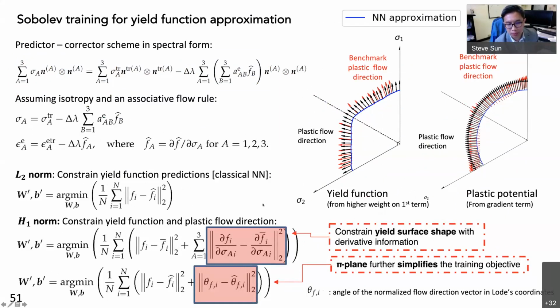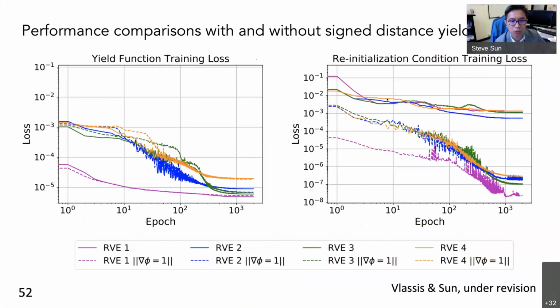We can also use the plastic strain increment to introduce a non-associative flow rule, as this example shows. We don't necessarily need to change a plastic potential. We can, but we can also compare the rotations between the stress gradient and the plastic flow direction to generate a non-associative flow rule. This is actually the difference between simply training a yield surface and assuming the yield surface is assigned different functions.